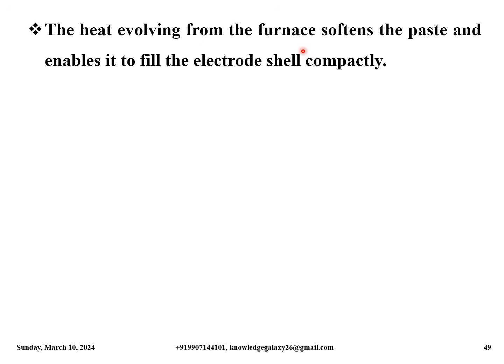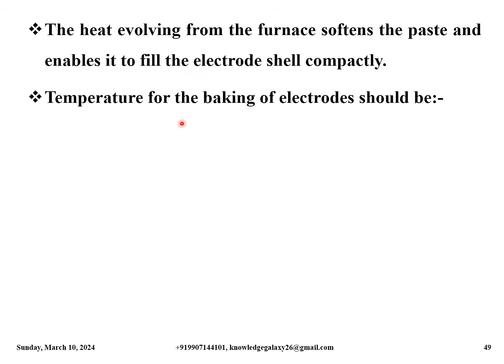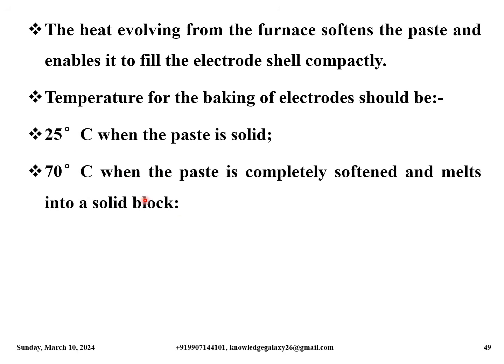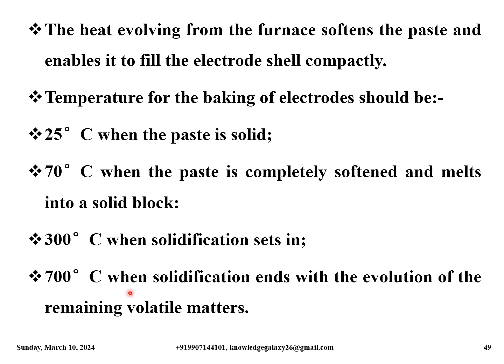The heat evolving from the furnace softens the paste and enables it to fill the electrode shell compactly. Temperature for the baking of electrodes should be as follows: 25 degrees Celsius when the paste is solid. Next, 70 degrees Celsius when the paste is completely softened and melts into a solid block. Next, 300 degrees Celsius when the solidification sets in. 700 degrees Celsius when the solidification ends with the evolution of remaining volatile matters.